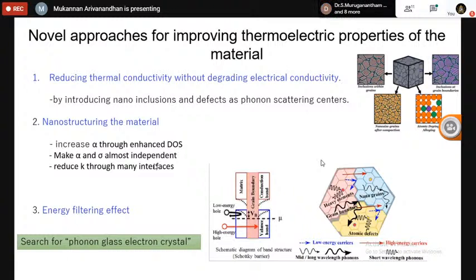By doing this kind of nanostructuring, you can play with the DOS, density of states of the material, and that will lead to independently control the electrical conductivity and Seebeck coefficient. And also, by creating this kind of nanostructured material, you can create a lot of interfaces with the grain boundaries. So these kind of interfaces will have some kind of selectivity of carrier transport, and that will lead to scatter the phonon as well, and that will lead to reduce the thermal conductivity.